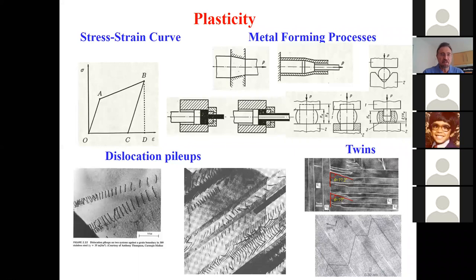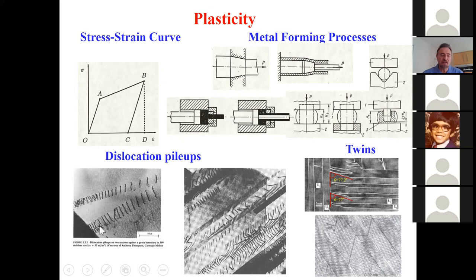I will start with some simple definitions. This is a schematic stress-strain curve. If you are moving along this line, loading and unloading, and there is no residual strain, this is elastic deformation. If you go further and after unloading we receive residual strain, this is plastic strain — we have hysteresis. This is the essence of plasticity phenomenon, and all metal forming processes are based on it. The main mechanism is related to nucleation and motion of dislocations — here you see dislocation pile-up against a grain boundary — and also twinning, grain boundary sliding, and some others.